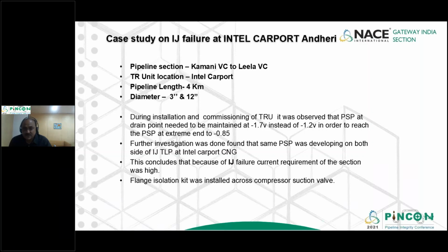During installation and commissioning, it was observed that the PSP at the drain point needed to be maintained at minus 1.7 volt instead of minus 1.2 volt to reach the PSP at the extreme end of minus 0.85. Because it is a CNG station, the pipeline has to come out and go to the compressor. We found that the PSP was developing on both sides of the IJ at this TLP at the Intel Carport, so we figured out that it was because of the IJ failure. Because it's an online station and we cannot cut and replace the IJ, we put a flange isolation kit across the compressor suction valve.